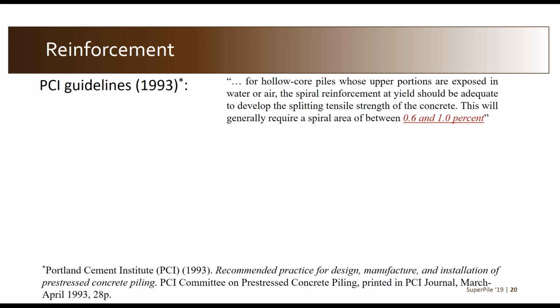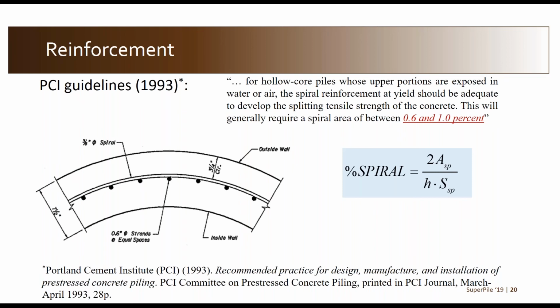There's an often cited report from the Portland Cement Institute from 1993 about pre-stressed concrete piles, including hollow cylinder piles, which has commentary directly on this issue. It actually says that the spiral reinforcement should be designed to carry the splitting tensile strength of the concrete. So in other words, the tributary area that corresponds to one spiral, the spiral ought to be able to carry the force that the concrete has when it ruptures in tension, so that if that occurs, the load is immediately transferred to the spiral reinforcement. And as a rule of thumb, they point out that that usually takes between about 0.6 and 1% as a spiral reinforcement ratio, which is defined like this for a hollow cylinder pile: 2 times the area of an individual spiral bar divided by the product of the wall thickness, the outer versus inner diameter, and then the pitch. So for the piles in the middle section on this project, that ratio is about 0.4%. So it is below what they recommend as a rule of thumb, providing at a minimum to resist cracking, which of course occurred.